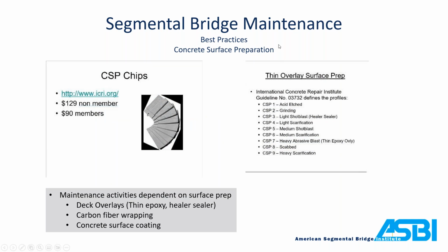Surface prep, again, with concrete remediation and maintenance, concrete surface preparation is critical. You need it for your overlays, wearing surface overlays, thin epoxy overlays, crack injection, carbon fiber wrapping. Concrete surface coating is all dependent on the prep. You'll see in specifications a lot of times they call out a CSP, a concrete surface profile, and this could be a number. You see over here CSP 1, 2, 3, all the way through 9, and kind of what it alludes to. But if you're not familiar with what a CSP 3 is, it's hard to tell the contractor when to stop doing the prep or if they need more prep. The International Concrete Repair Institute does sell these CSP chips, and these are really valuable in the field because you can hold it up against concrete and say, yep, it matches my profile on my chip, you're good to go. So I highly recommend if you're a construction inspector and you have a project to carry a set of these chips in your truck with you.